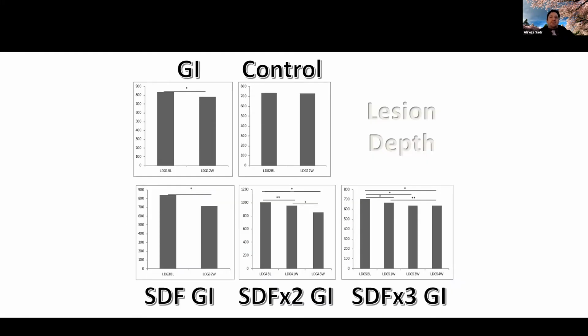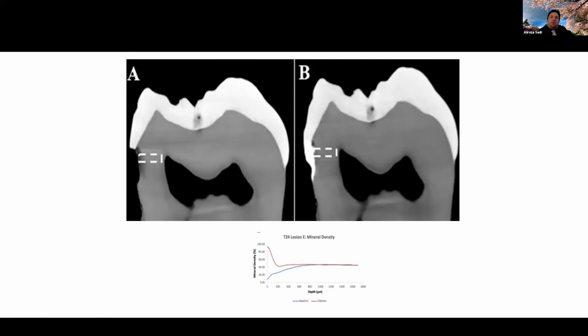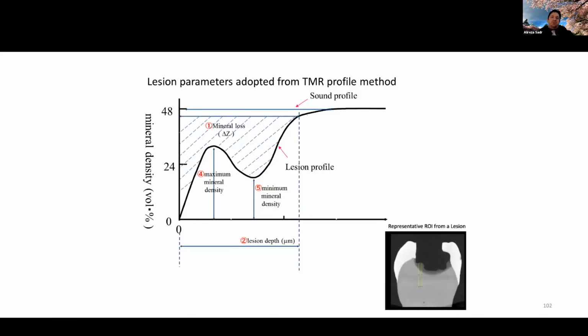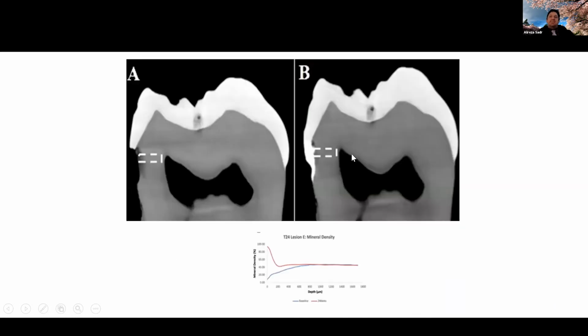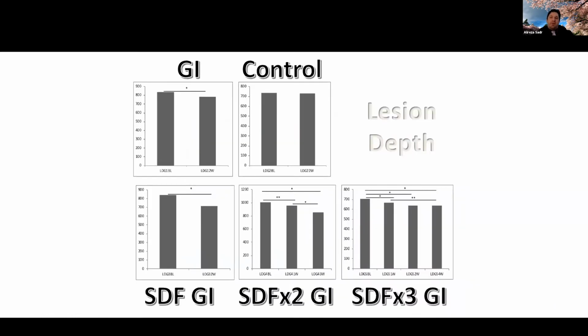Just gonna get to the results, and we looked at 2 different measures. We looked at the lesion depth, and we look at the mineral loss. Now, the lesion depth doesn't really change a lot if you know the microradiography technique of measuring the lesion depth. The lesion depth doesn't really change a lot with SDF or even glass ionomer application. The reason is that some demineralization will remain, but it's all about rehardening the dentin.